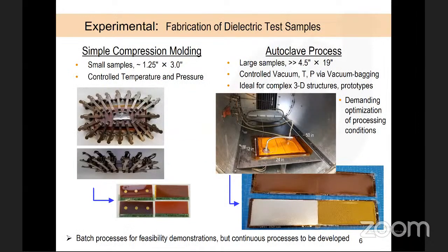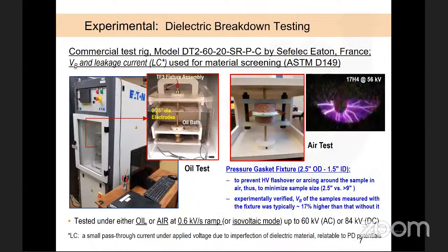MMEI samples were fabricated by a simple compression molding for small dielectric test samples, or an autoclave process for large samples, as well as complex 3D structures and prototypes. Both were a batch process, but continuous processes are also being developed. VB was the primary property used for material screening and optimizations. We used the commercial system following the ASTM standard. The testing was done either in oils, typically with small size samples, or in air, which is closer to the actual surface environment, but required much larger samples because of high voltage flashover.